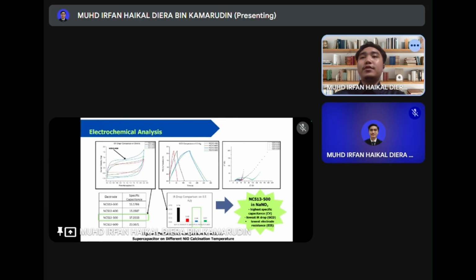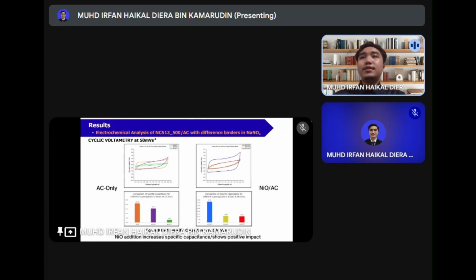This confirms that 500 degrees Celsius is the ideal calcination temperature for NiO to achieve strong synergy with AC, resulting in enhanced supercapacitor performance. This slide shows cyclic voltammetry (CV) results at 50 mV/s for different binders in two systems. On the left side are AC-only electrodes, and on the right side are NiO-AC composite electrodes.